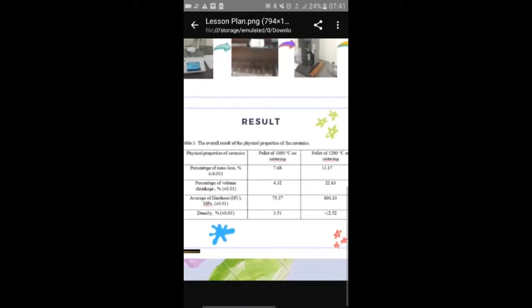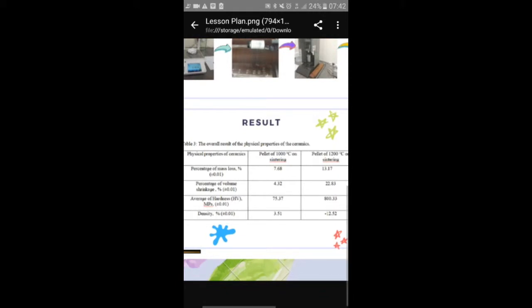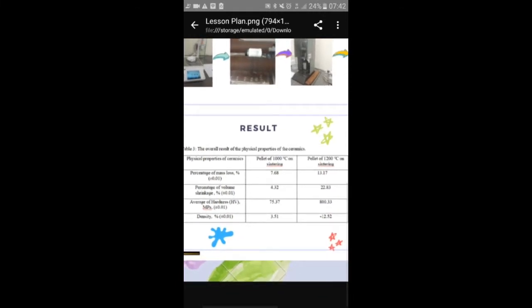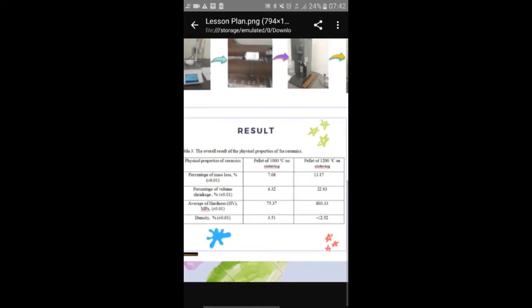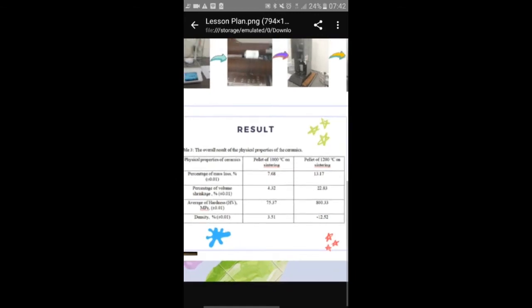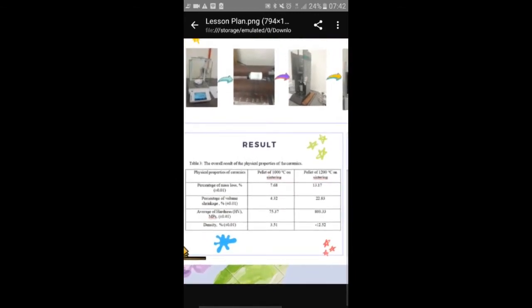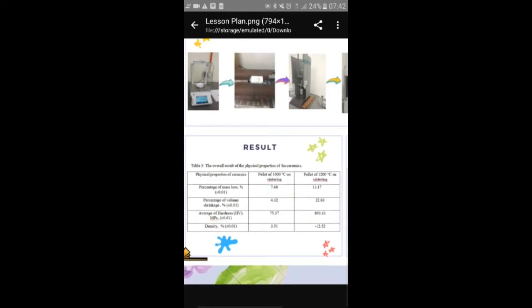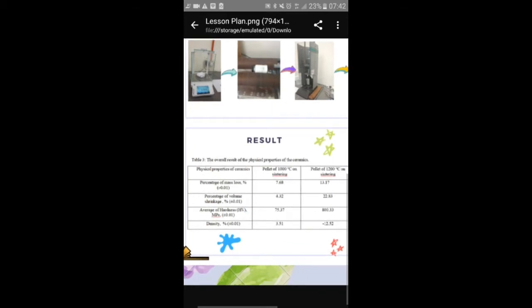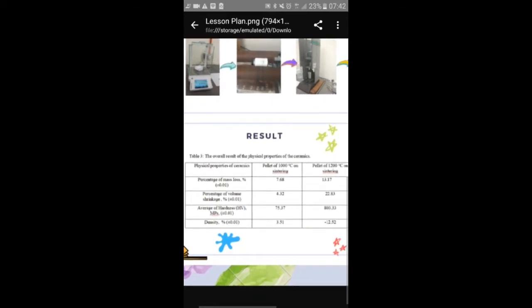The percentage of volume shrinkage. In this table, it shows an increase in the percentage of volume shrinkage from 4.32% at 1000 degrees Celsius to 22.83% at 1200 degrees Celsius. The sintering process with high thermal energy may lead particles to join together and simultaneously reduce the volume of pores between them. So the percentage of volume shrinkage may increase due to the decreasing volume of pores and pore surface area.